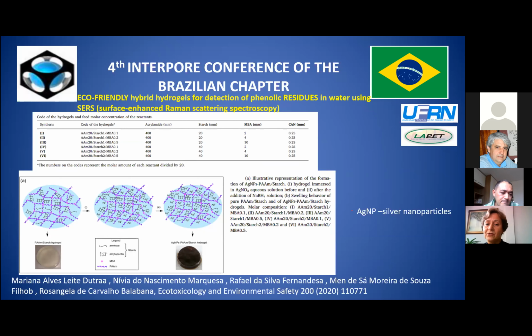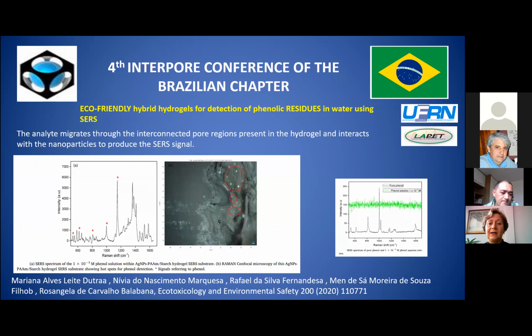This spectroscopic technique is very useful to enhance the detection of some organic molecules. In our case, we selected phenol. So in the picture, we can see the hot spots of silver nanoparticles, and these hot spots can increase the signals of the Raman spectrum. So here you can see signals of very high intensity.